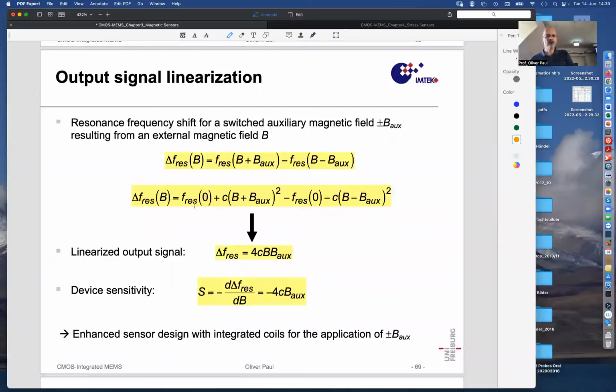And if the resonance function is a quadratic function, as it seems to be, to first order, then you can write it as such, and the other one as such, and then you simplify, and at the end you have delta resonance is equal to 4 times this arbitrary constant that represents this parabolic curvature of our curves, and then B times B aux. So we have a response that is proportional to the external field. That's exactly what we want of a sensor. And it's proportional to a parameter that we can even set technically by applying an auxiliary field. If we don't do that, then we have nothing. If we make it strong, then we have something strong. And the absolute sensitivity would then be the change of the resonance frequency per magnetic field, which is obviously this number.